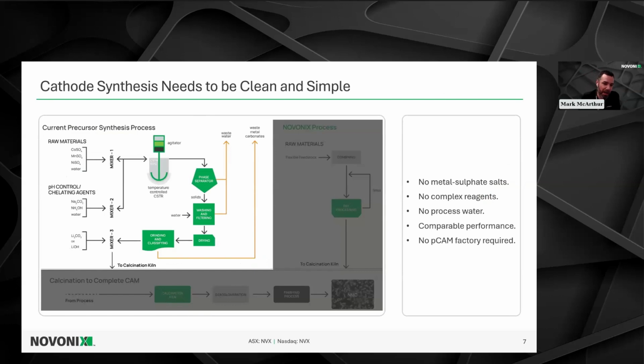So again, I like to compare our process to what is conventionally done. And here I'm focusing in on the precursor synthesis process, that PCAM step I mentioned earlier. To make a precursor cathode active material, you take metal sulfate containing materials, so a cobalt sulfate, manganese sulfate, nickel sulfate, and combine that with water in a continuous stirred tank reactor at elevated temperature. To that, you're also adding some complicated reagents, including sodium carbonate, ammonium hydroxide, and more water.